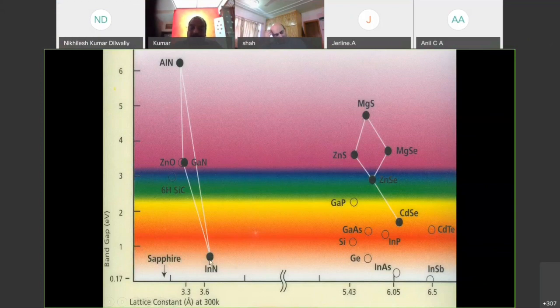Currently, at Anna University, we have been working for the last 10 years on materials known as gallium nitride, indium nitride, and the alloy with aluminum nitride. These are very interesting because you can tune the band gap from something like 6 eV to close to 1 or 1.1 eV. This is the most interesting aspect of it. This is called band gap engineering.